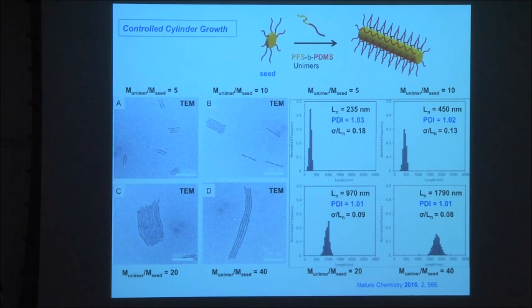I didn't mention this. The TEM only shows the core of the micelles, because the core contains iron, so it scatters much more strongly. So each of these, the corona is kind of invisible here, but that's what actually spaces out these structures. And they prefer to interact with one another through the corona than interact with the surface. So that's why they bundle. So in solution they don't bundle, but after solvent evaporation they tend to.